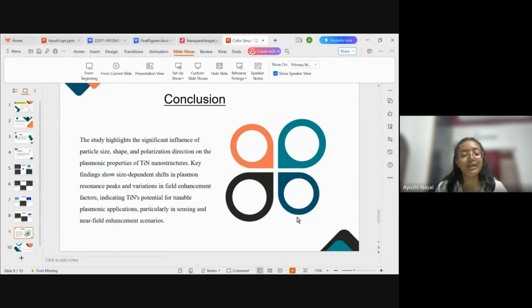From all of this, my conclusion was the study highlights the significant influence of particle size, shape, and polarization direction on the plasmonic properties of titanium nitride nanostructures. Key findings show size-dependent shifts in plasmon resonance peaks and variation in field enhancement factor, indicating titanium nitride's ability for tunable plasmonic applications, particularly in sensing and near-field enhancement scenarios.